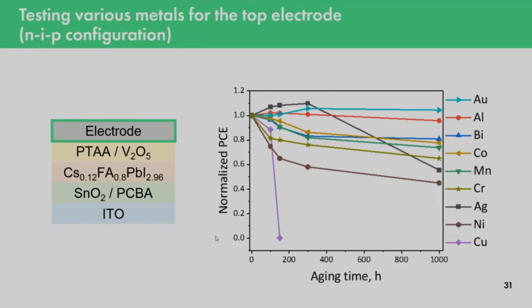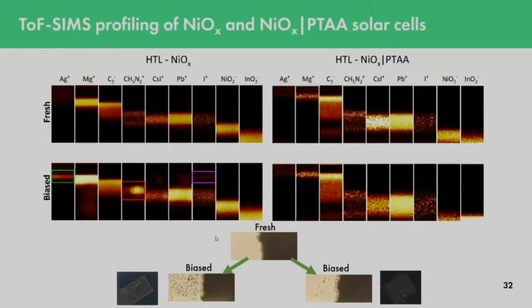Like gold, aluminum. Aluminum is also quite traditional, and gold and different other materials, actually all that was available for us. And we found out that the most stable solar cells would actually not be with the silver electrode, but with gold and aluminum electrodes. One of the reasons why this happened can be demonstrated on this TOF-SIMS analysis of nickel oxide PTAA solar cells, which also demonstrates why PTA is important and what's happening on the electrode side. So you can see that when we have pure nickel oxide as hole transport material, we can observe the complete destruction of the perovskite layer.